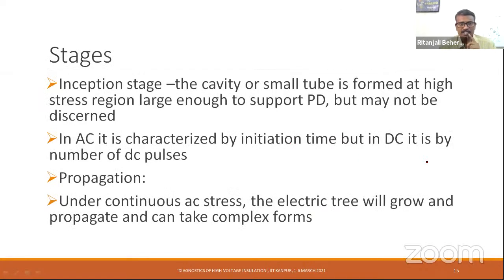Stages: inception stage and propagation stage, those 2 stages. The cavity or a small tube is formed at a high stress region, large enough to support PD, but may not be discerned. This is what I said: in the initial stage, things take place in the micro void, which is very small, and the PD taking place will not be detected by the detector. In AC, it is characterized by the initiation time, but in DC, it is by the number of pulses. Propagation: from the formation of the first branch until it breaks down, and the complex form it takes, that is the second stage, the propagation stage.